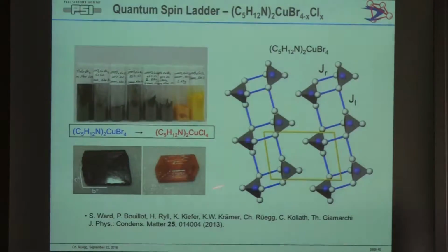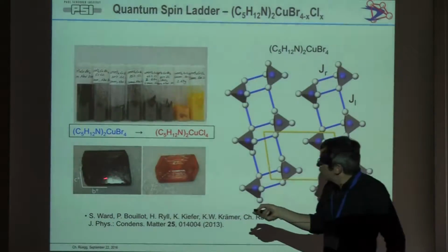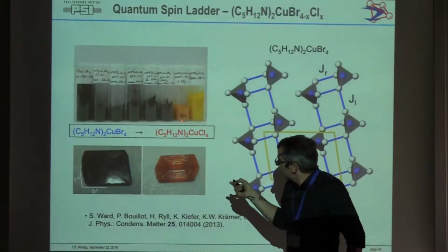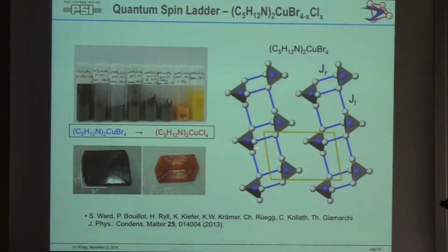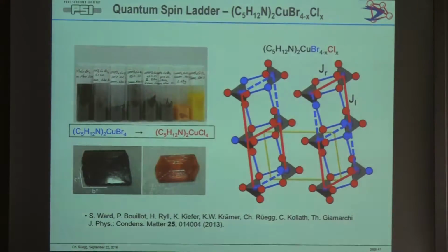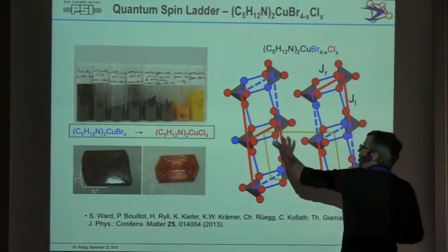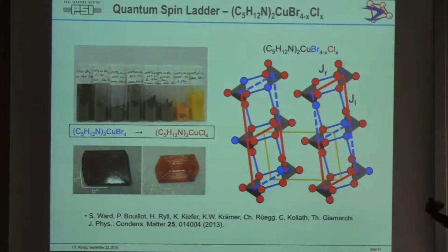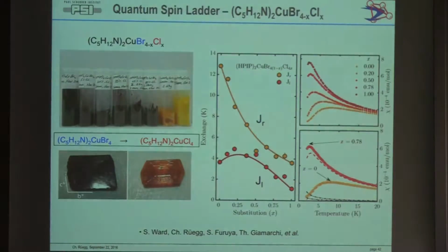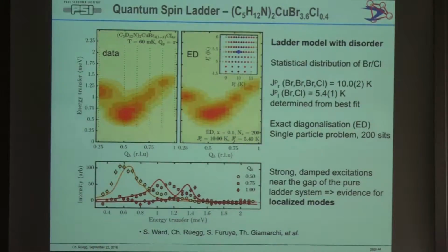One way to do that is you take this material, and as I already showed, you have these two versions of it, and essentially you can start to mix those. And something interesting happens. You basically have the exchange paths, which are the rung and the leg exchange parameters. So you do a mixing of chloride and bromide, and they statistically distribute on the lattice. You can then make a statistical model for the variation of the J's in the ladder. So you can study effects of quenched disorder in this case, and look at the effects of localization and so on. We have been doing that in the last few years, trying to characterize all of these different compositions, extract averaged exchange parameters, and also some from the excitation spectrum, and you find very beautiful effects.